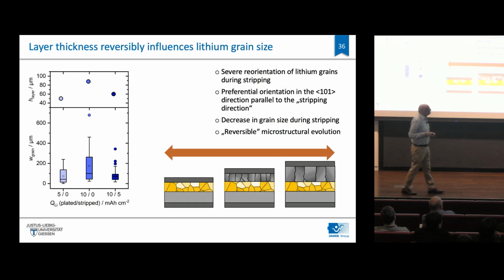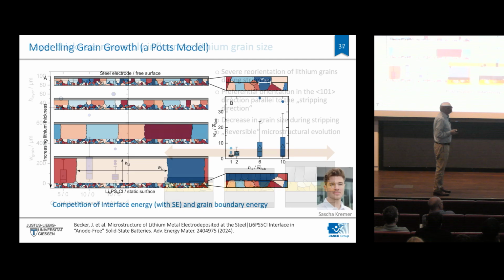But before I tell about that in the final part, we really proved meanwhile that, in fact, with a thicker growing lithium film, the grains always get thicker due to grain growth. So originally, let's say with the 5 milliamp hours per square centimeter lithium being grown, you have smaller grains. Well, doubling the thickness, grains get bigger. And then reducing it again, stripping, reproducibly, the grains get smaller. So it's really reversible. Grains grow, grains shrink. That's a function of the thickness of the lithium film because these grain boundaries can move relatively easily due to the fast transport, not only within the grain boundaries, but also across the grain boundary.